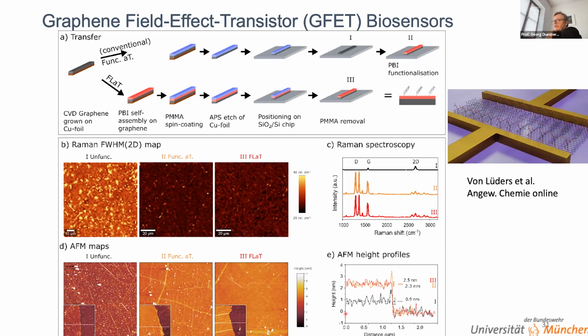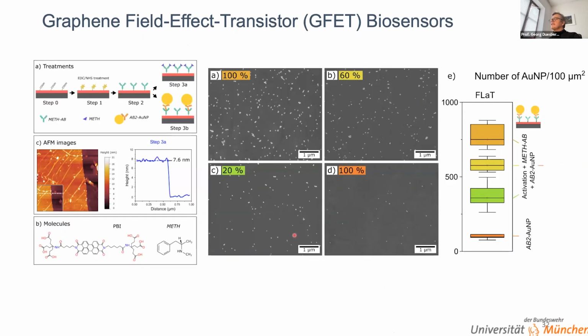Here's a comparison of the height of the unfunctionalized layers and the functionalized layers with PBI. As shown here, we actually get more or less a monolayer, or what we believe are self-assembled monolayers, of these molecules on top of the graphene. Those molecules carry carboxylic functions, which we use further for the attachment of antibodies, which is shown in the next slide.